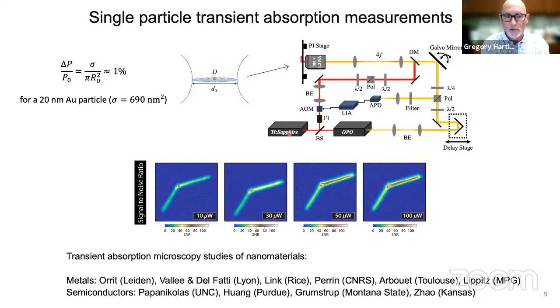So that's sufficient to detect and study single particles that have dimensions on the order of 10 nanometers. Okay, if you have the right laser system, it's not that hard to see a single particle. You just have to have a stable laser and focus very tightly. And you do need to do high frequency modulation to get the signal out of the noise. Okay, so that's what we do.